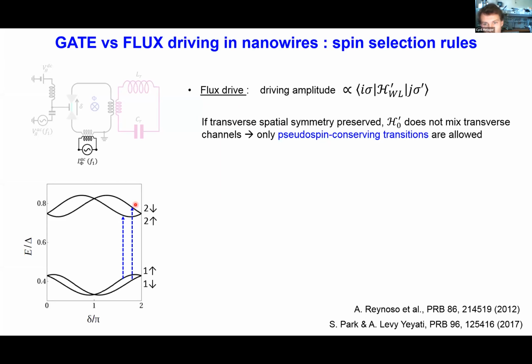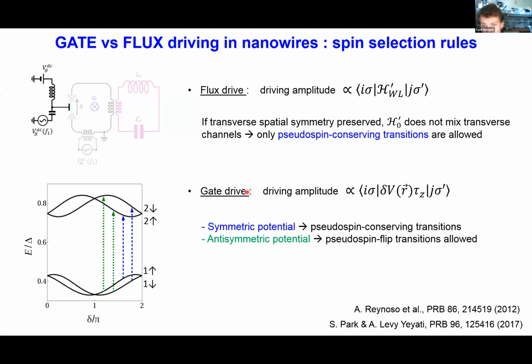2 down. However, if you drive the system through gate, then the AC signal that you send induces a perturbation in the electrostatic potential that fills the nanowire. And this breaks the rotational symmetry and couples the states on different subbands. So in this case, spin flip transitions would be allowed. So you would be able to excite 1 down to 2 up and also 1 up to 2 down. But let me stress here that this only works if the induced potential has some anti-symmetry in the section of